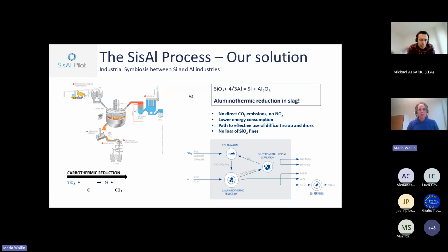So what we instead produce, you see we produce silicon and alumina in the slag. So silicon is a metal, alumina in the slag, and we put in aluminum dross or scrap as reductant. And that means no direct CO2 emissions. We also have other emissions that we decrease, like NOx, which is a problem of carbon. We need less energy because this is an exothermic process as compared to the previous one, which is endothermic.